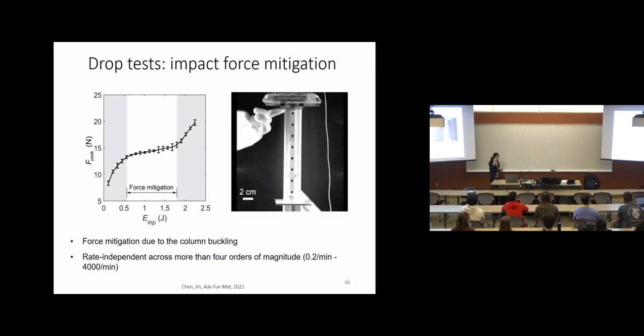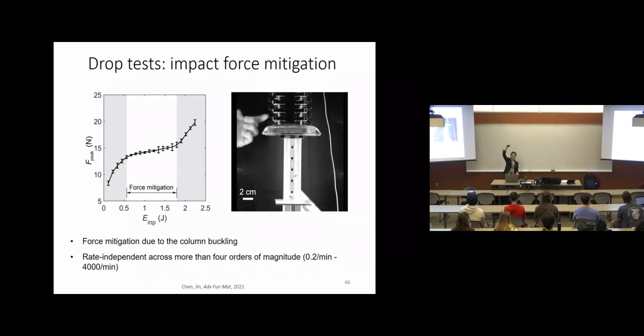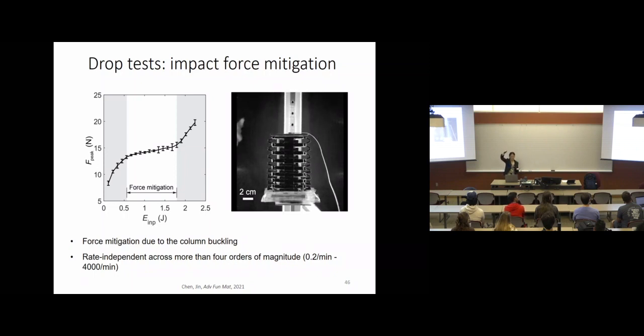Here I'm further showing you a dynamic test. We drop this material from the top with some heavy load on it, so there's an impact at the bottom. Then we measure the force on the top and plot it with respect to the energy input. In a wide range of energy input, the force reaches a plateau, indicating force mitigation. From the video, you also see not a lot of rebounding of the material, indicating energy dissipation. Moreover, this force is comparable to the peak force we measured for the static case, which indicates rate-independent behavior over a wide range of loading rates.